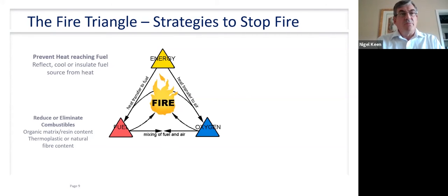The other way we can do this is to prevent heat from reaching the fuel. So we can reflect or cool or insulate the fuel source from the heat. So if we've got a barrier system or a foil on the surface or something that's reflective or insulating, then we can actually create a barrier between the heat and the fuel. So in some cases, this could be a veil. Sometimes we even use things like metal flakes in a coating to provide some reflective properties.